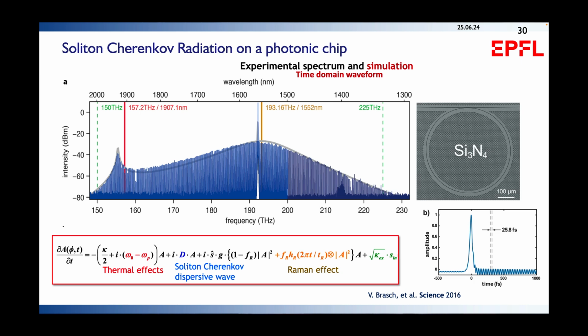Now you asked about thermorefractive noise. The thermorefractive noise in these microcombs would be the fundamental linewidth. If you look at a soliton pulse stream that comes out and it was not stabilized, that pulse stream has a phase noise that is governed by intrinsic temperature fluctuations of the resonator. And the smaller the resonator becomes, the larger it becomes. For an optical clock, what would be important is how fast you can lock the comb. This can be extremely efficient if you use piezoelectric actuators. If you had an optical clock application where you really want to transfer the phase noise of your primary laser line to the comb, this can be done very faithfully, using the piezo actuator and laser frequency as two independent control knobs.